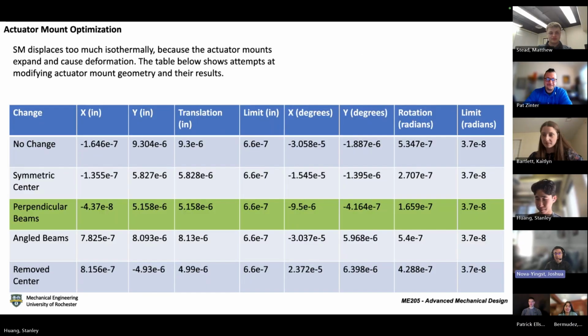So at least for the isothermal displacement, the design that adds two perpendicular beams to the actuator mounts decreased the isothermal displacement the most. We did not have time to run any additional simulations, so we don't know if this hurts the vibrational mode or decreases our lowest margin of safety. But we are also adding more weight, which was one of the factors. This one ended up not being the heaviest. I think, oh no, I'm sorry, this one was the heaviest. So that's the other issue. This brought our weight up by almost 0.8 pounds to about 17.7. So for future work on this, that is something to bear in mind.